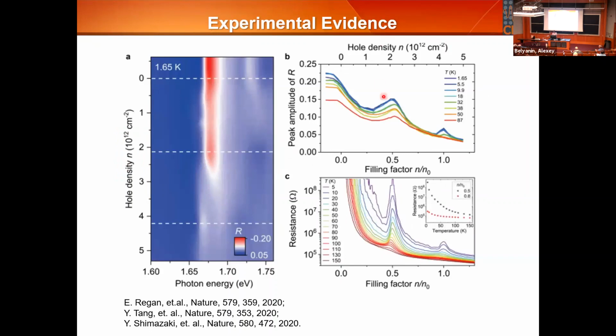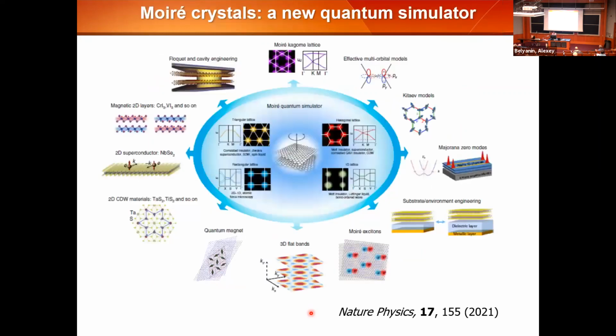There's some initial evidence that has emerged last year, but I would say these results are all going to be debated in the next 5 years, if not longer. A lot of people have speculated about the large array of problems you can simulate in the Moiré superlattice. I've talked very limitedly about Moiré excitons today, but you can simulate a quantum magnet: by simply changing the twist angle, you can create an antiferromagnetic or ferromagnetic material. We know they're superconducting. They can be superconducting or insulator simply by changing the twist angle.